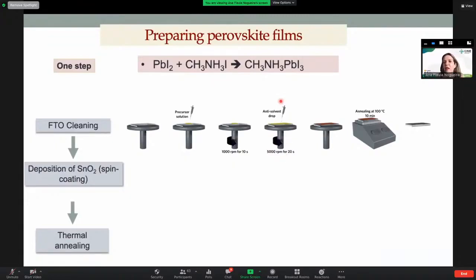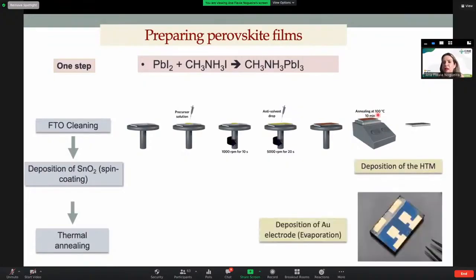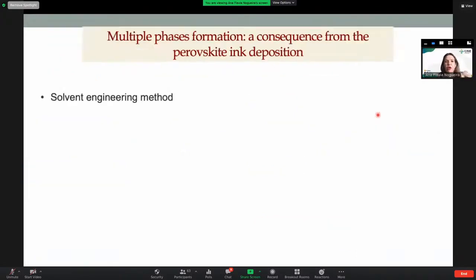Then I have annealing, another 10 minutes of annealing at 100 degrees Celsius. Then there is the deposition of the hole transport material, and then we deposit the contact by evaporation, then we have a device. I just want you to pay attention to this antisolvent method, okay?